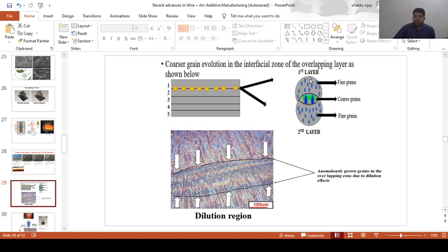When I am depositing the second layer, when the heat input is very high, the second layer will slightly impinge into the first layer, which is called dilution. It will look just like a Venn diagram. In this diluted area we can observe some kind of coarser grain formation, which I have mentioned over here. This kind of coarser grain is nothing but columnar dendrites. I have shown that kind of dilution region in optical micrography as well.